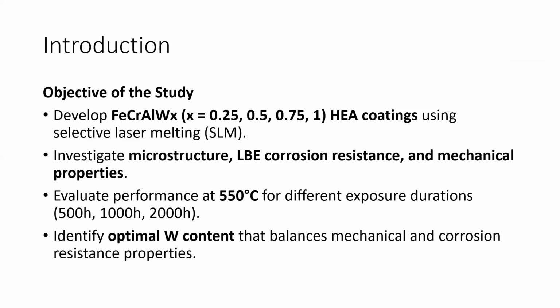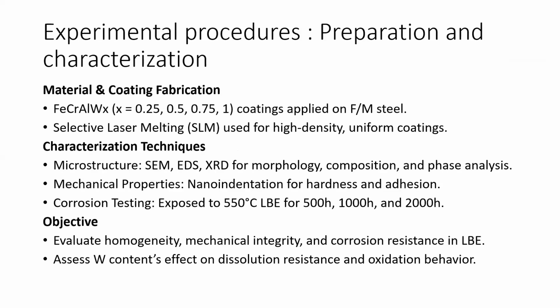So, the objectives of the study are to develop FeCrAlWx HEA coatings with x equal to 0.25, 0.5, 0.75, and 1 using selective laser melting (SLM). Investigate microstructure, LBE corrosion and mechanical properties. Evaluate performance at 550 degrees Celsius for different durations like 500 hours, 1000 hours, and 2000 hours. And last, to identify the optimal tungsten content to balance mechanical and corrosion resistant properties.